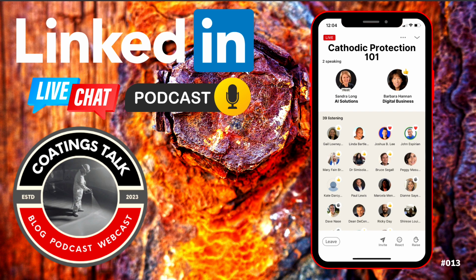Let's talk about the history of cathodic protection. Cathodic protection was first described by Sir Humphry Davy in a series of papers presented to the Royal Society in London in 1824. The first application was to the HMS Samarang in 1824. Sacrificial anodes made from iron were attached to the copper sheath of the hull below the waterline, dramatically reducing the corrosion rate of the copper.